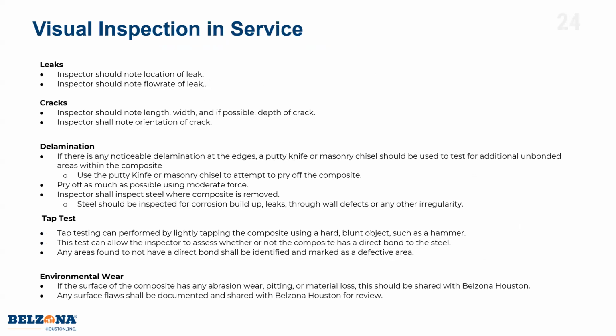So going over what you're going to look for in the visual inspection, you're going to look for leaks. The inspector should know the location of a leak. Is it in the middle of the repair? Is it at the end of the repair? If you see a leak in the middle of the repair, you're thinking something happened there, installation or process wise. Note any cracks, and look for delamination. If you see the edge lifted, you can get a putty knife underneath and try to rip it off and see if it's just an adhesion issue.